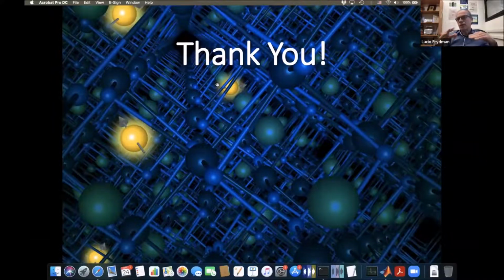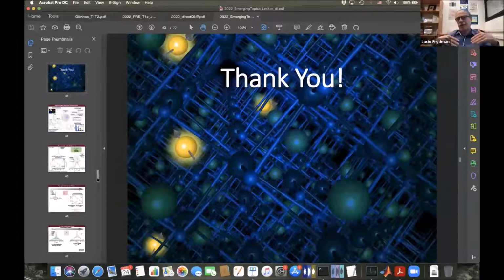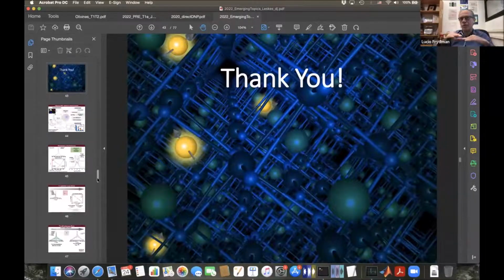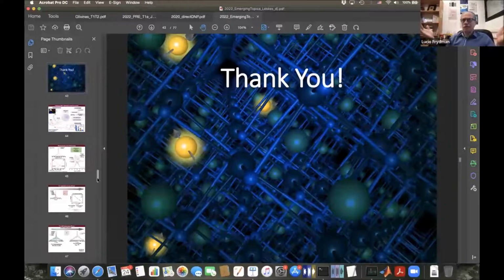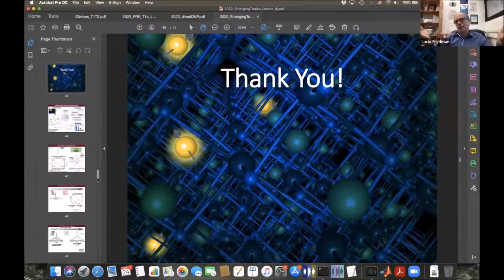But then again, when you have an enhancement and you turn off the microwaves, I guess you also have to somehow deal with the distribution of this T1 of the nuclei, which, although these are quadrupoles, I guess you assume are all dominated by paramagnetic relaxation. So how do you do that? Do you go for very long recycle delays, or do you measure the enhancement as a function of different delays? Because I imagine that some of the nuclei that enhance in the DNP, because they are far from the electron, you don't see them, because when you turn the microwaves off, the T1 is just too long.